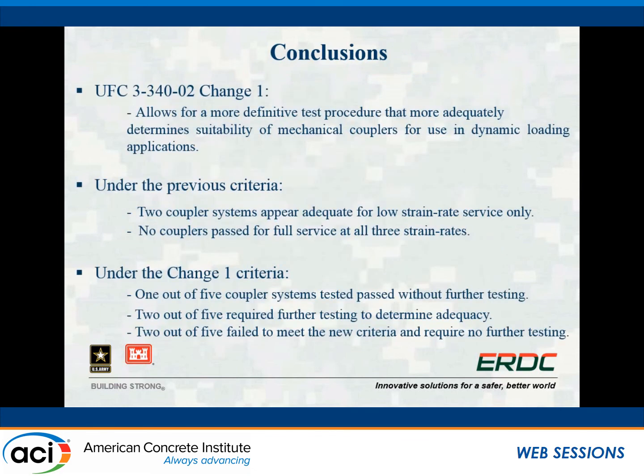So just some conclusions from that testing that was done. Again, in UFC Change 1, we've incorporated guidance to actually do this testing. Under the previous testing, if we use the previous criteria, only 2 out of all the modern coupler systems that were investigated would meet those requirements in quasi-static conditions. None of them would meet the requirements in dynamic conditions.